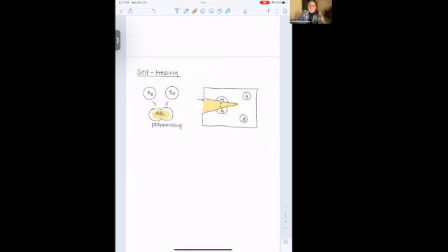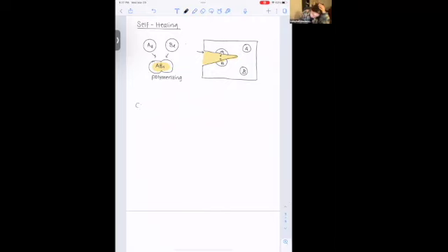And one of the applications where self-healing would be interesting is in construction materials. And so the application I looked at was self-healing concrete. And normal concrete actually has some slight ability to self-heal on its own anyway. It's called autogenous self-healing. And it's basically just when unreacted cement particles are hydrated, it just ends up forming that same cement paste that was there in the first place.